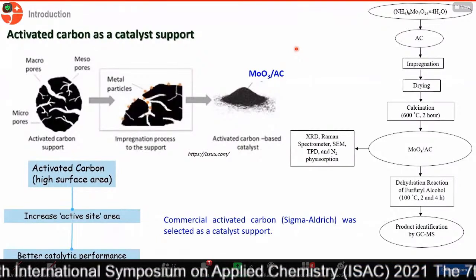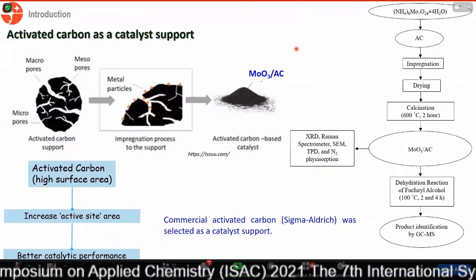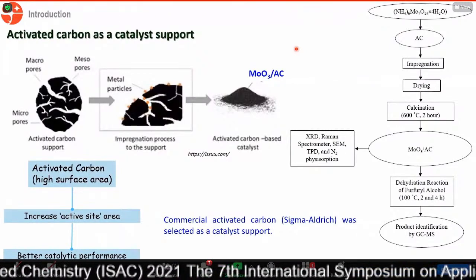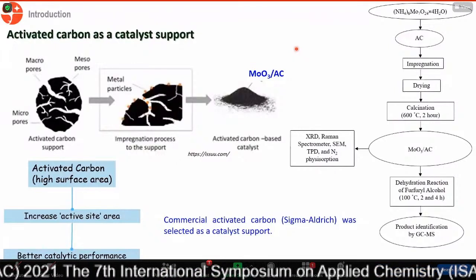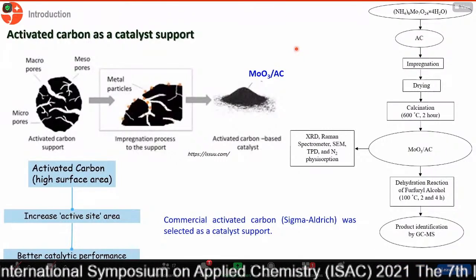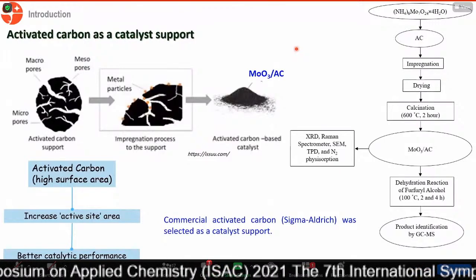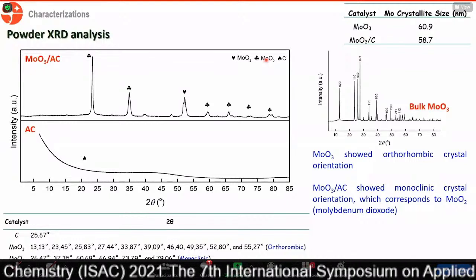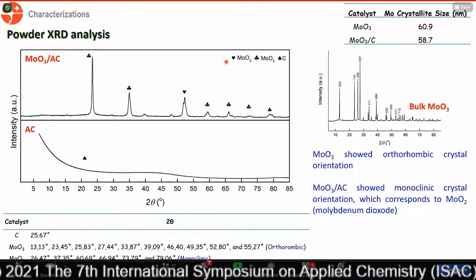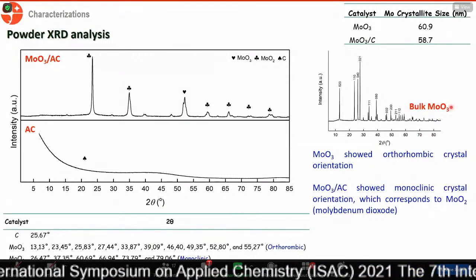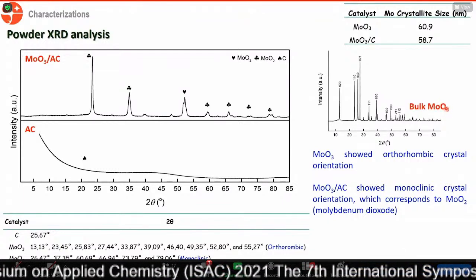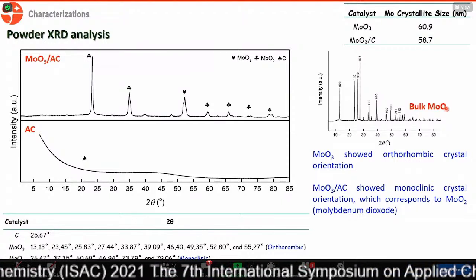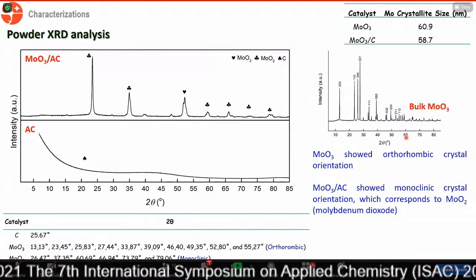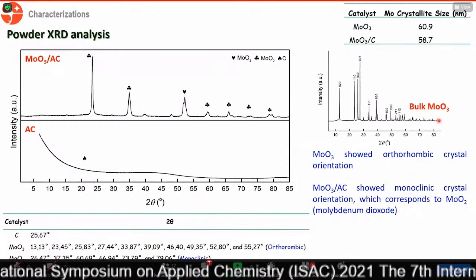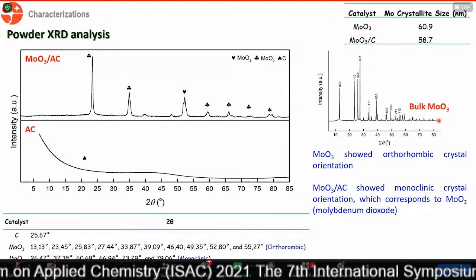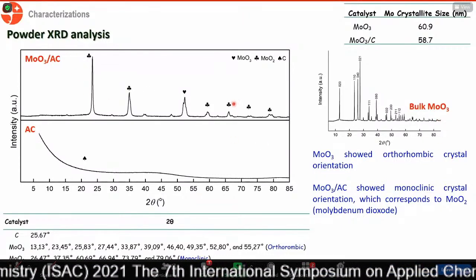The loading of molybdenum oxide was done by simple impregnation at room temperature, and then after drying and calcination at 600 degrees Celsius for 2 hours, we obtained the catalyst. The synthesized catalyst was further used for the dehydration reaction at 100 degrees C for 2 and 4 hours. In addition to our synthesized molybdenum oxide on the activated carbon, we also prepared the bulk molybdenum oxide that we obtained by direct calcination of ammonium heptamolybdate at the same temperature for 2 hours. And this bulk molybdenum oxide showed orthorhombic crystal orientation.